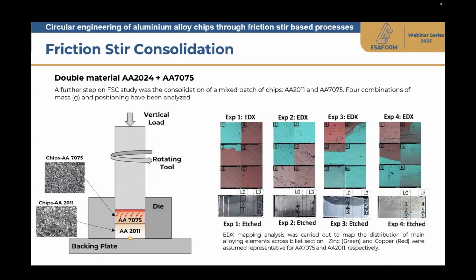Well, here we have in turn another step of the investigation we've been carrying out, namely the possibility to obtain a billet made by 2 different alloys, 2 different aluminum alloys. So the idea in this case was to combine 2 different kinds of chips in order to get a mixed material or a mixed billet with these two alloys.